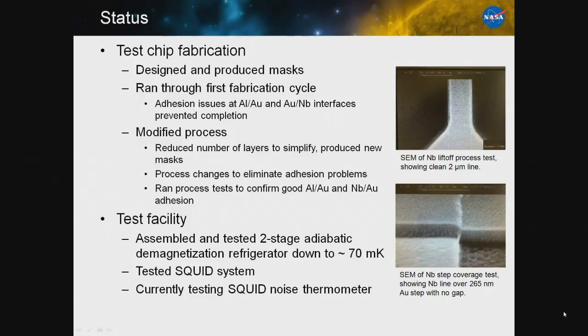And these are just a couple of SEMs, one showing a nice clean 2-micron niobium line, and another showing a nice clean 2-micron line that's going over a gold step with no gapping. So the test facility, as you saw in the last picture, we've assembled it. We've operated it down to 70 millikelvin. We've tested the squid, and currently we are reading out noise temperatures using a resistor from an old chip that we had.